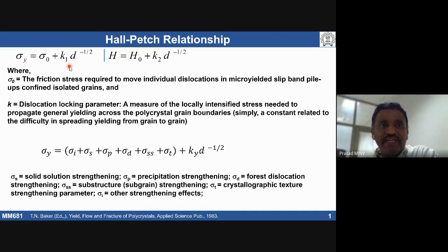It's basically a governing equation which describes how the yield stress of a material depends on the grain size of the material. Here, sigma y equals sigma naught plus k times d to the power of minus 1 by 2. Sigma naught and k are called Hall-Petch constants. Each one has its own physical meaning.